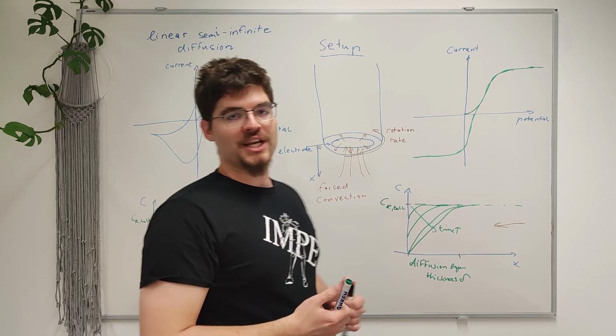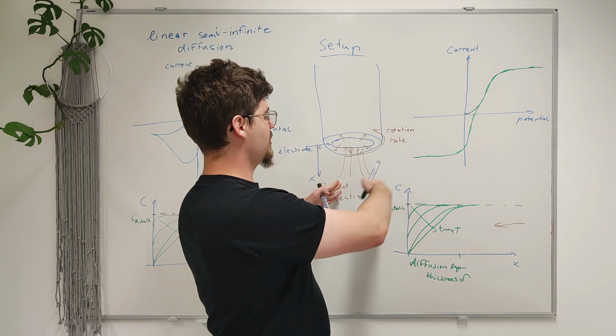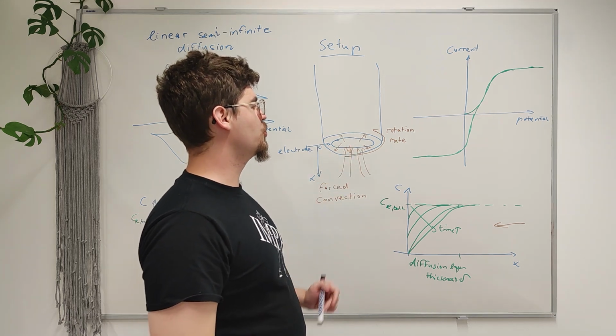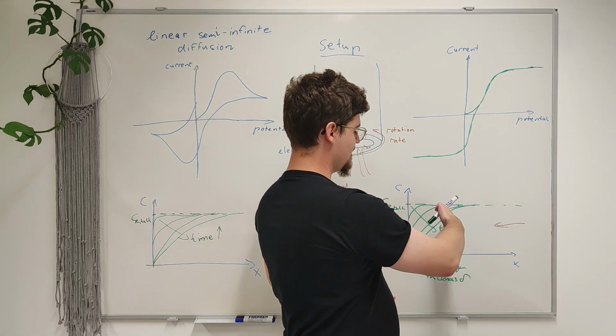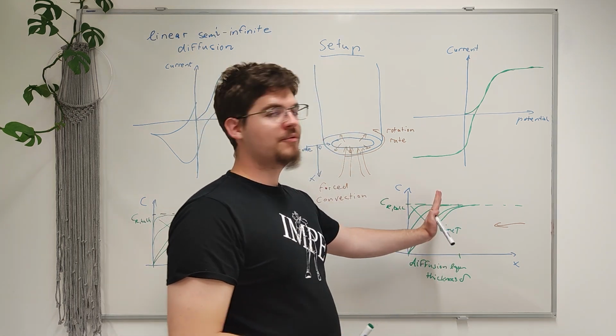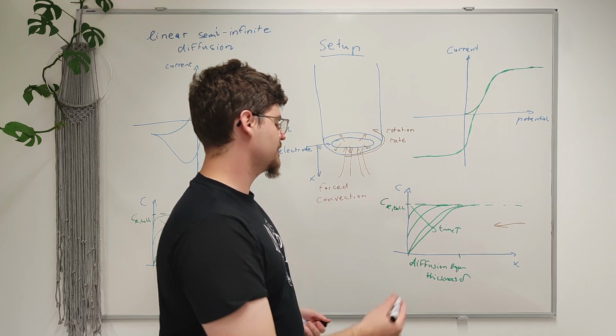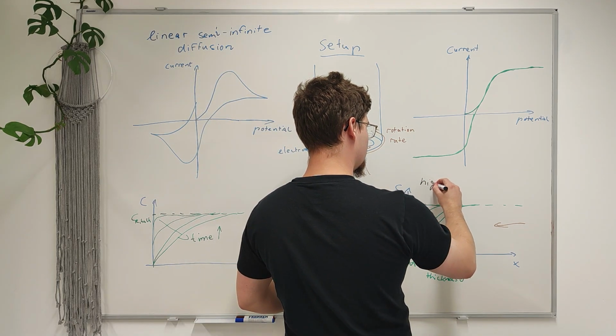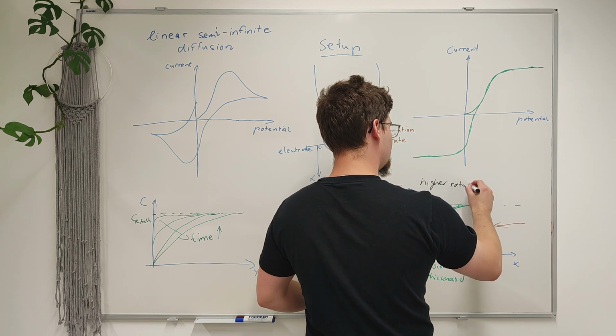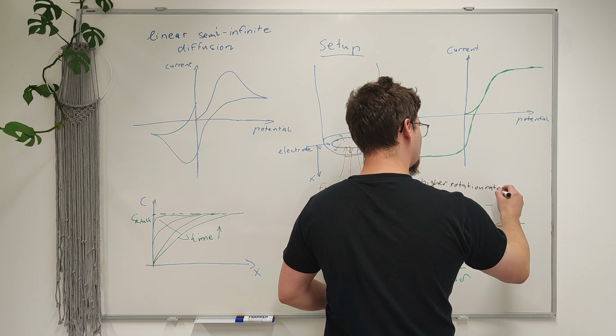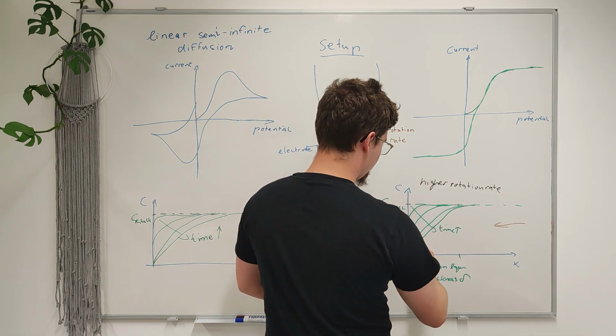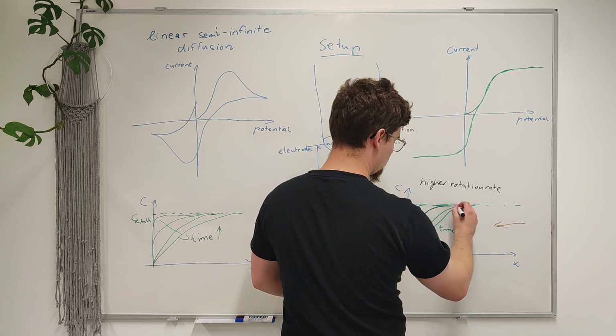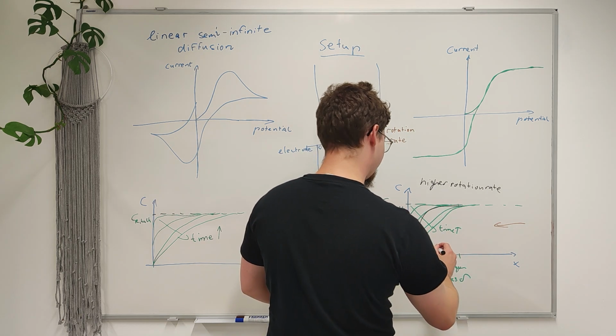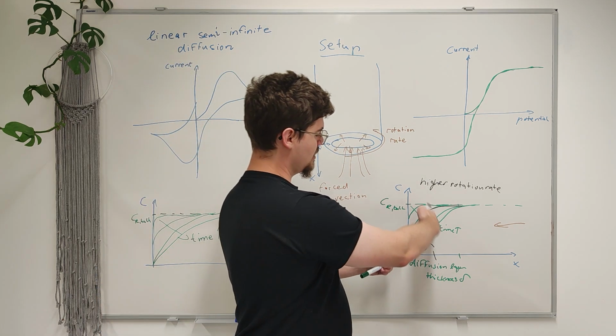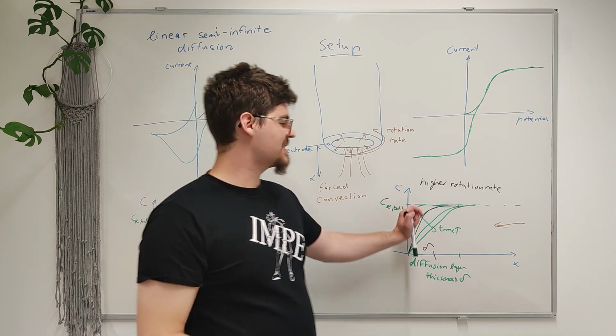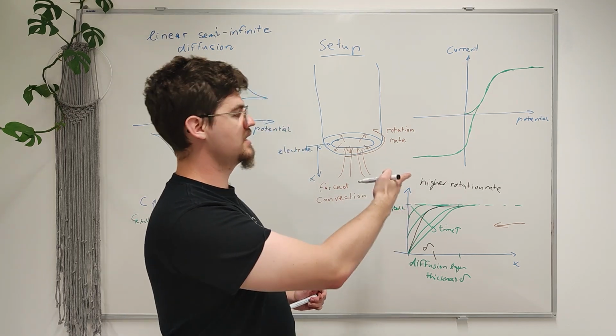Now, if we increase the rotation rate, it increases the velocity at which bulk electrolyte moves towards the electrode, and this constrains the diffusion layer even further. So for a higher rotation rate, our limiting diffusion profile may, for example, look something like this, where we now have a smaller delta here. In that case, because the diffusion layer that we can now achieve is smaller, the gradient is higher, and the current plateau is also higher.